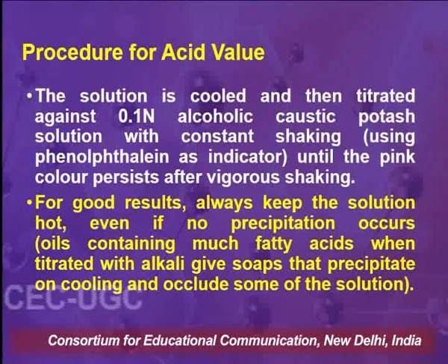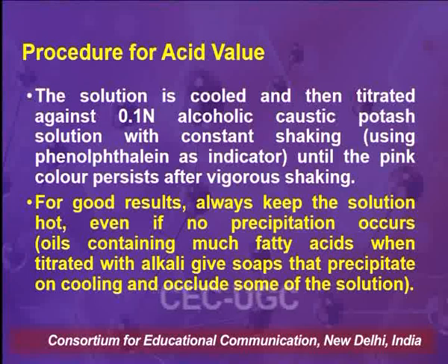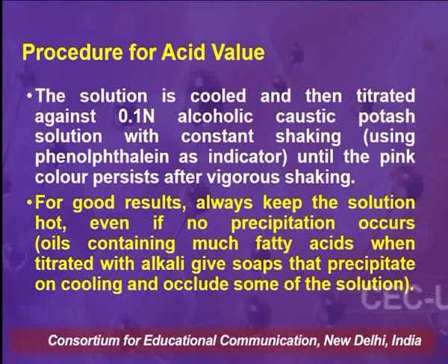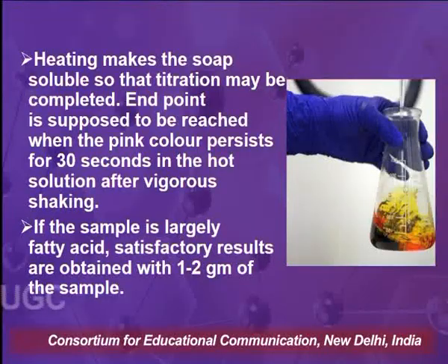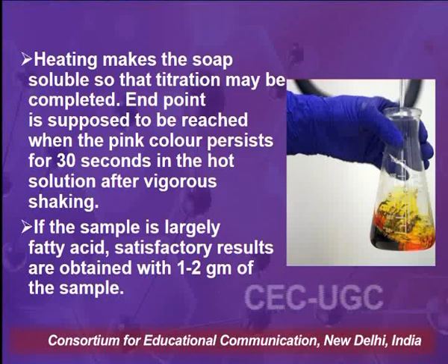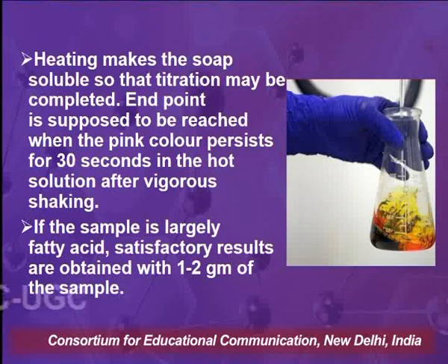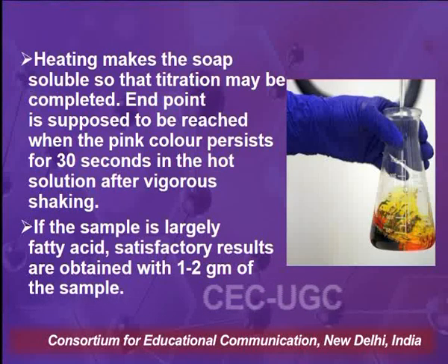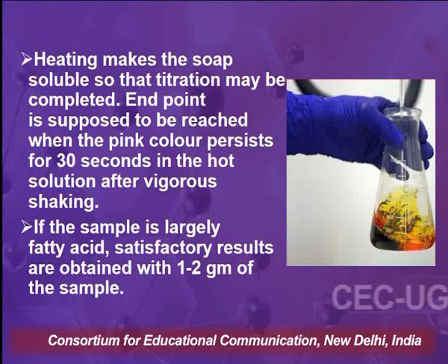For good results, always keep the solution hot even if no precipitation occurs, because oils containing much fatty acids, when titrated with alkali, give soaps that precipitate on cooling and occlude some of the solution. Heating makes them soluble so that the titration may be completed, so we keep the solution hot. Endpoint is supposed to be reached when the pink color persists for 30 seconds in the hot solution after vigorous shaking. If the sample is largely fatty acid, satisfactory results are obtained with 1 to 2 grams of the sample.